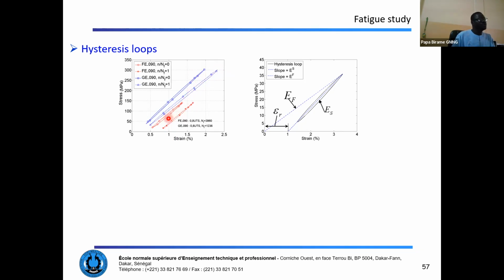And when we focus on the flax epoxy composite, the contrary is noted: at the end of life of the flax epoxy composite, you have an increase of the slope of the hysteresis loop, which corresponds to the secant modulus.